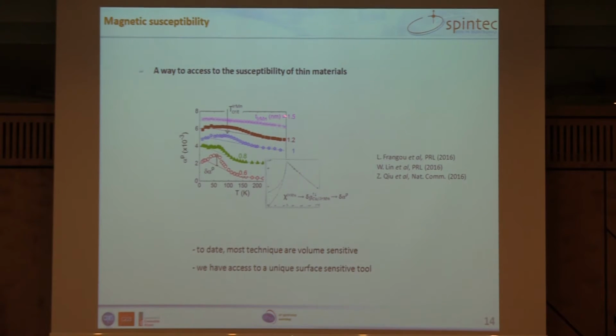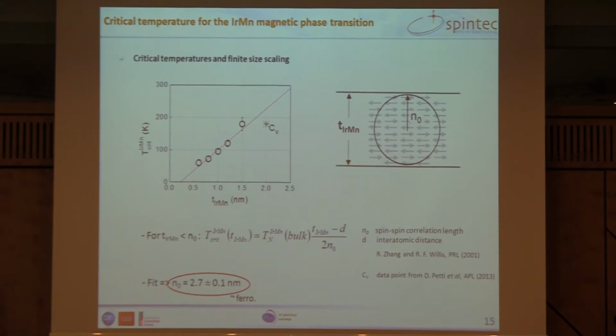So from this, if we spot the critical temperature, we can plot the evolution of the critical temperature as a function of the thickness of our antiferromagnet. And these data points also fall on a straight line. And actually, there are some very simplistic models that describe the evolution of the critical temperature as a function of a material's thickness. This is a model by Zhang and Willis in 2001. It is a very, very simple model, but it proved quite robust for different kinds of antiferromagnetic materials.